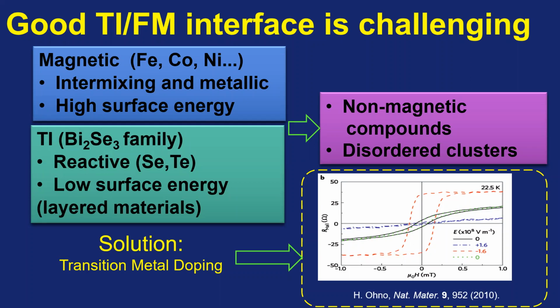The second step, how can we introduce the ferromagnetic order in the topological insulator? The very straightforward way is we just deposit the magnetic material on top of this topological insulator. The conventional magnetic materials, usually iron, cobalt, nickel, are very reactive and have very high surface energy. But the bismuth selenide family materials are selenium and tellurium based, with low surface energy. So when you deposit iron, nickel, or cobalt on top of the topological material, they will react with each other and make the interface not very good.